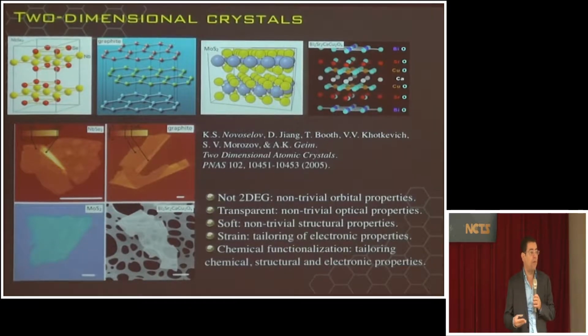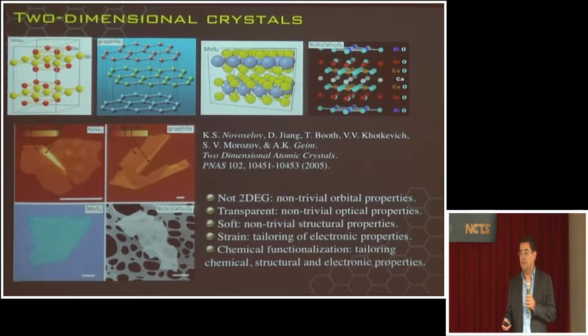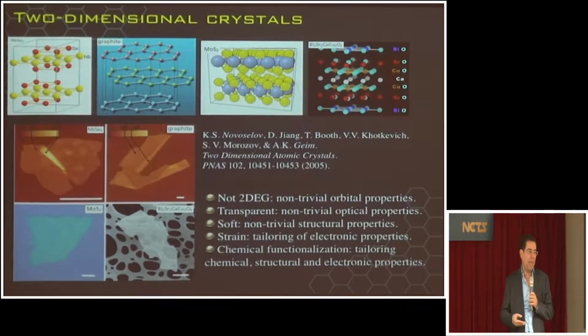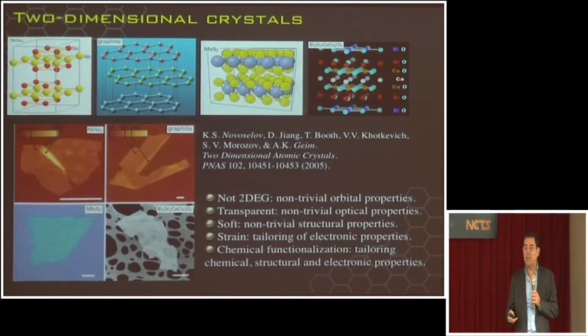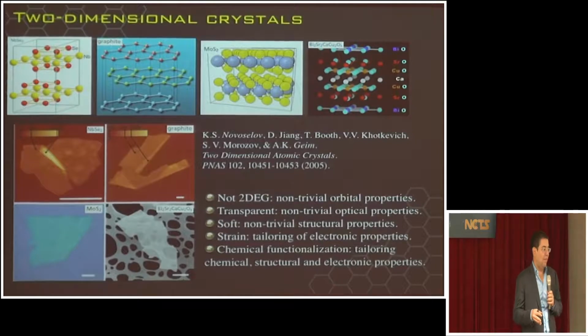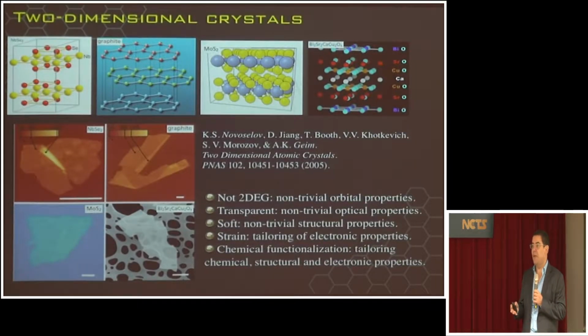Actually, compared to other materials, graphene is pretty boring from the electronic perspective, okay? It's a non-interacting system. It's described by a very simple equation, and everything that was predicted theoretically for graphene was confirmed experimentally. I don't recall a single theoretical prediction that was not confirmed. Why? The material is too simple. Okay? So there is no complexity in graphene. So it's very easy. For us it was a great playground, but it's not so challenging from the theoretical perspective. These other materials are way more challenging. They are more complex. Okay? They have much deeper physics behind. Okay? And I want to talk a little bit about that.